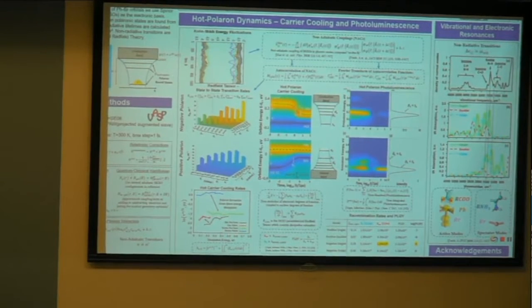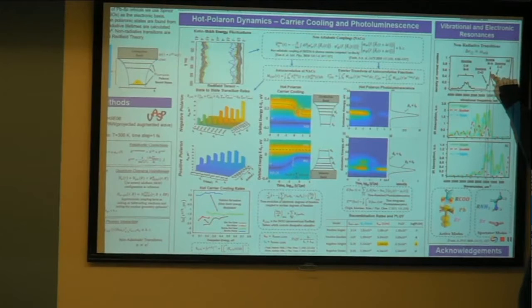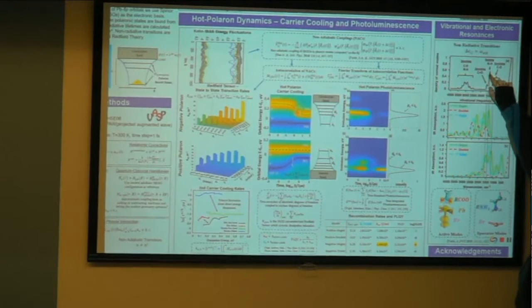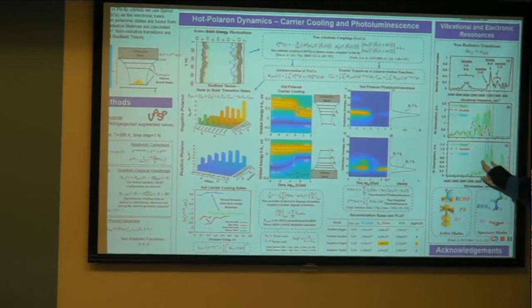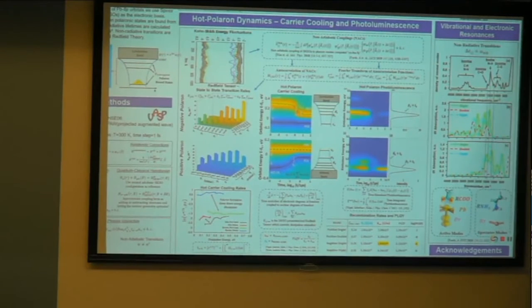And what we find is that for this negative singlet, it's in resonance with an ammonium that's on the surface, whereas for the other models, they're essentially in resonance with carboxylic acids that are on the surface.